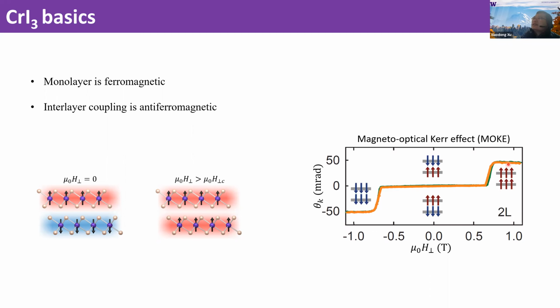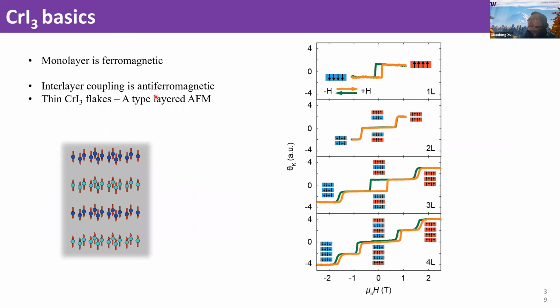This is just a summary. Basically, CrI3 is an A-type layered antiferromagnet, and the individual monolayer is ferromagnetic. That's why for odd numbers of layers, we always have one layer of net uncompensated magnetization. We see a hysteresis loop, and as the field increases, we see spin flip transitions. But for even numbers of layers, the net magnetization vanishes at zero field, and as we increase the field, the spin flip transitions happen again. We see these steps.